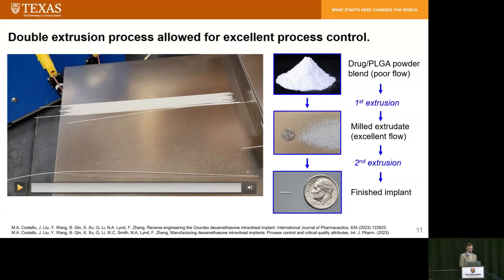We got this double extrusion technique from the Ozurdex patent, and that's good because it means that any extent of PLGA degradation that occurs during extrusion in our process will hopefully be quite similar to whatever degradation occurs in Ozurdex itself.